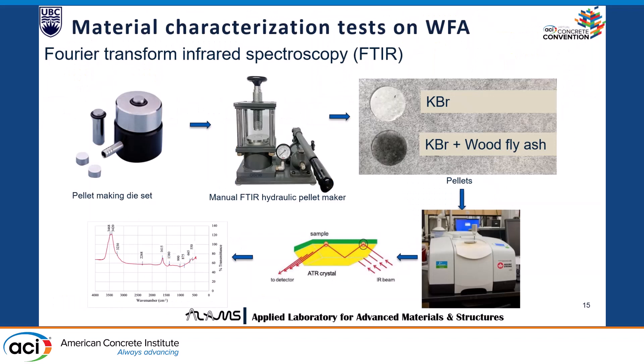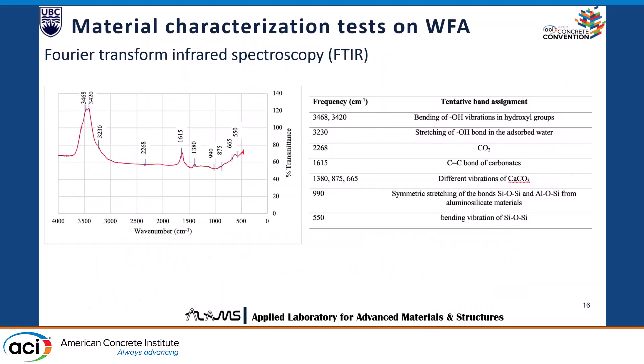We also did Fourier transform infrared spectroscopy. From the bands, we found the presence of water — although it was oven-dried, we found the presence of O-H ions. We also found calcium carbonate, Si-O-Si, and Al-O-Si bonds.